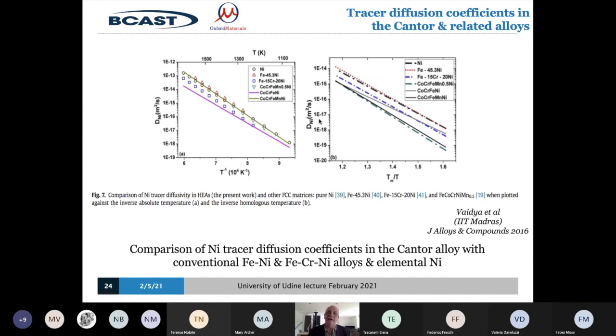It's not surprising. The lattice is incredibly variable and incredibly distorted. So if atoms are going to move around, they've got to push their way through a much more complicated set of environments, and they find it very difficult to do it. So that means that they're very resistant to degradation as a material, whether they're exposed to high temperature, or exposed to corrosion, or exposed to radiation damage. And the Cantor alloys are being looked at actively as temperature resistant, radiation resistant, and corrosion resistant materials for just that reason.